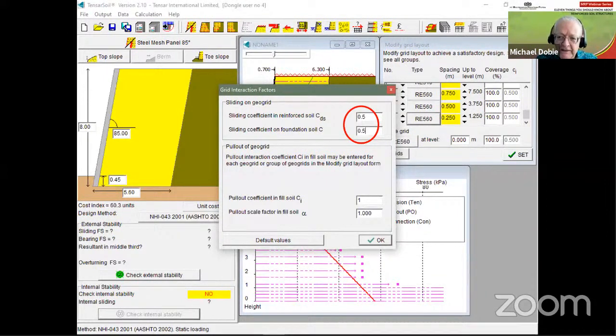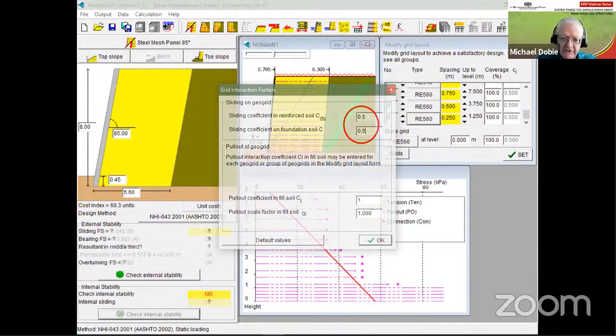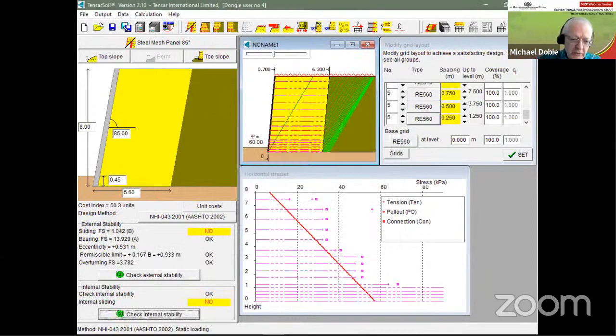It means that when you have a sliding interaction, you take half of the soil shear strength rather than the full soil shear strength on that sliding plane. And if we do that, and we analyze, we get all sorts of no's. You can see there sliding external stability and sliding internal stability. You see the yellowish and red no, because it's not adequate. And if you look on the cross-sectional diagram, you can see lots of sort of fat red lines indicating sliding over those layers of geogrid.